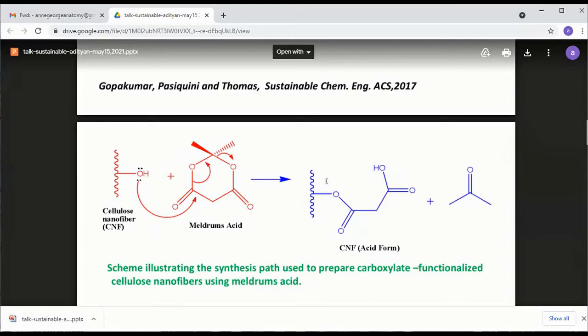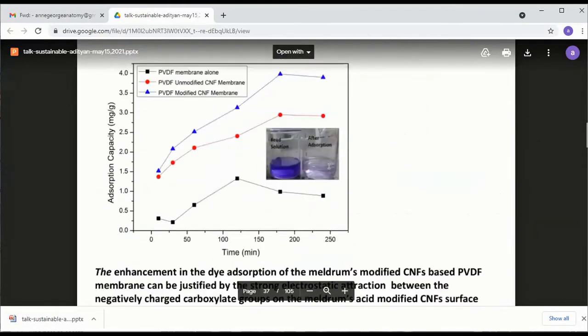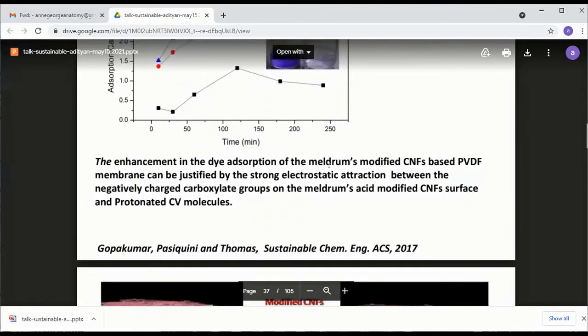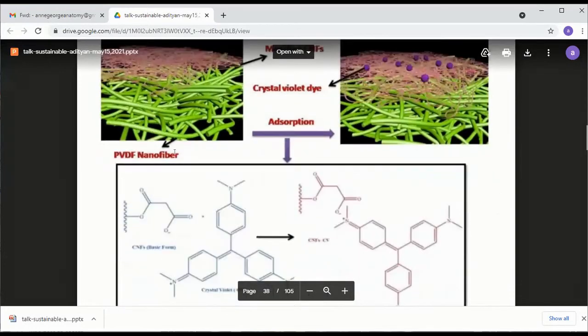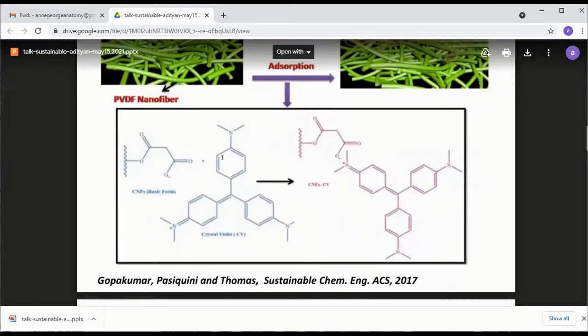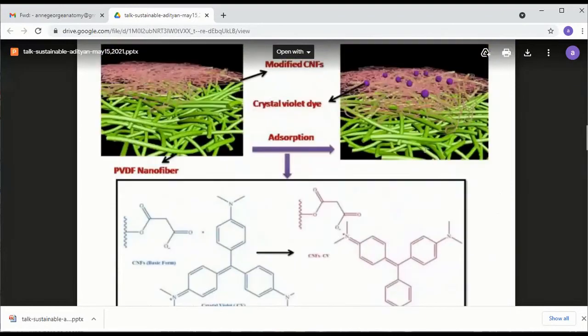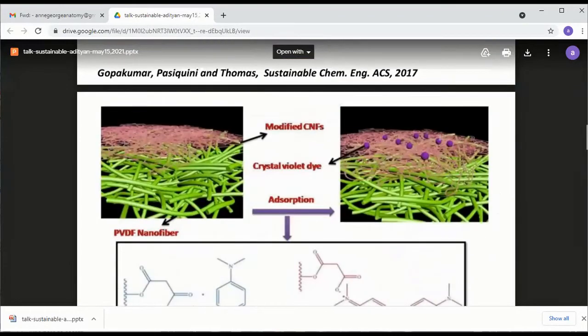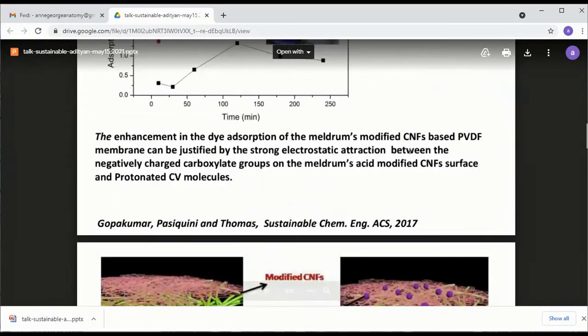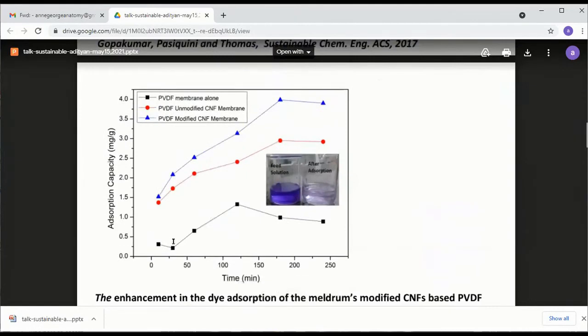And then you might ask, why did we do this chemistry? If we do this chemistry, look at this protocol. So you have nanocellulose with the CO minus group. This is the dye being used in the industry. And this dye can have electrostatic interaction. So all these dyes could be captured by nanocellulose by this interaction. So if you don't do this chemistry, you cannot have this sort of interaction. And you will find that our filter is able to remove all these crystal violet dyes. And you can see the efficiency of separation. This is the commercial filter that you get in the market for dye removal. Look at our filter. Our filter is much more efficient. The top one is chemically modified nanocellulose. This is unmodified nanocellulose.